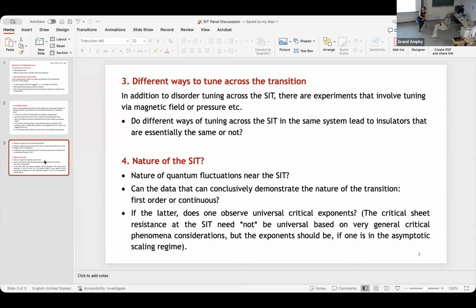But there is one small catch in the experiments where you see that small drop in the superfluid density. Is that superfluid density measured at gigahertz? Yes. So ideally, you should measure it at much lower frequency. This suspicion came to me only very recently when I was measuring the superfluid density with our resonator method in gigahertz. What we observe is that for thicker films and low disordered thicker films, we have the superfluid density exactly the same when we measure with the two-coil Lemberger method at kilohertz and when we measure with a resonator at 5 gigahertz.